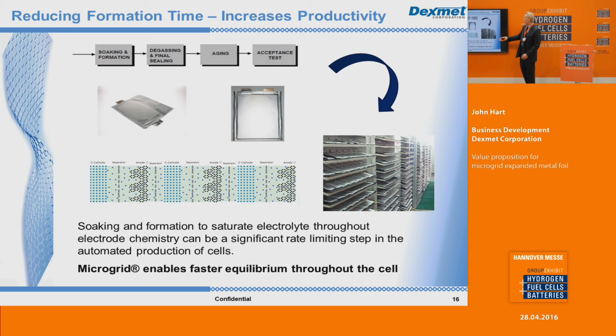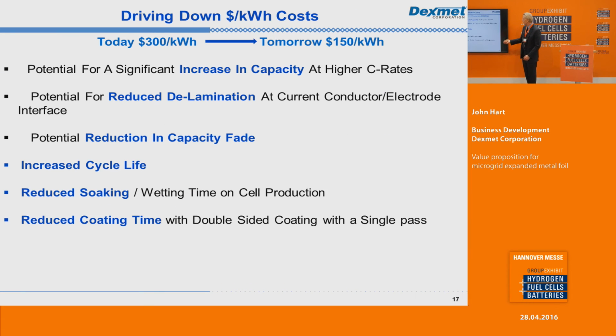So to summarize all of these cost savings, what we're looking at is the potential to significantly increase available capacity, significantly reduce delamination, increasing cycle life, reducing capacity fade, reducing soaking time, and also reducing the amount of coating time. So if you add all that up, we feel that there is a very profound amount of potential cost savings during the battery development process.